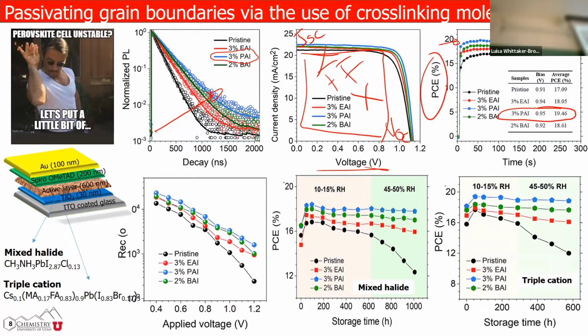Okay, so 10-15% relative humidity is fine in Utah. For 45 to 50%, we actually have to artificially make that because it doesn't get that humid. But then what we see is that with the propyl ammonium, we don't lose that much in stability.